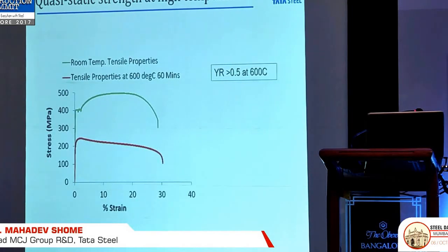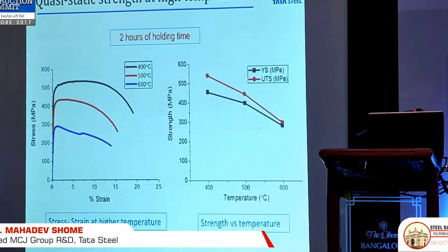And then these are some of the tests that we did to reinforce our findings. So this is the yield strength of this material at room temperature. At 600 degrees centigrade, it drops, but it still is above this value. So it doesn't come to 0.3, but it remains above 0.5. So you are able to prevent structural collapse of the building at that temperature. This is what happens at different temperatures. This is at 400 degrees centigrade, this is at 500, this is at 600.